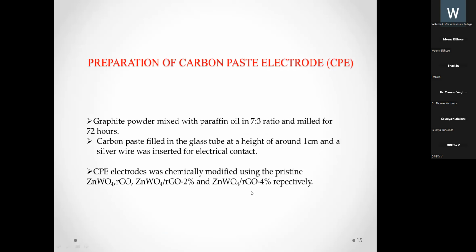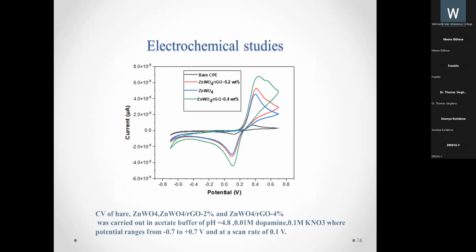The CP electrodes were chemically modified using pristine zinc tungstate, RGO, and zinc tungstate RGO 2% and 4% respectively. The corresponding electrochemical studies were done, and this represents a CV of bare zinc tungstate and zinc tungstate RGO 2% and 4% respectively. This was done using acetate buffer with a pH of about 4.8, and dopamine was used as analyte, and the concentration is about 0.01 molar.